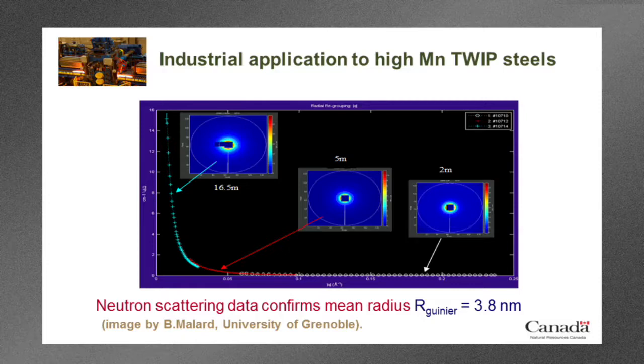So we took a bigger sample, thick samples, and did neutron scattering. This was with the aid of Benoit Malard, who was at the University of Grenoble. And what we found using the neutron scattering data was that the mean radius was 3.8 nanometers compared with 3.7 nanometers measured in the TEM, so we were very happy with that result.